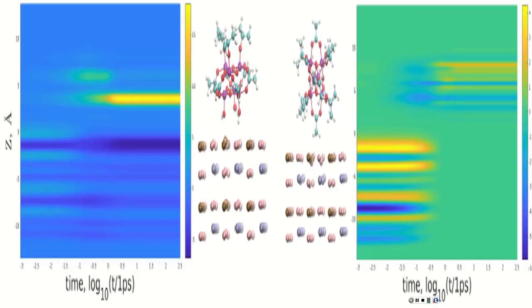And as time passes by, both electron and hole do migrate to titanium dioxide. So there is no charge transfer. Well, there is one very short transient charge transfer. By the way, it is similar to what Dan computed for your recent work. So, transient short period charge transfer, and then later lowest excitation, both blue hole and orange electrons stay on the acceptor. So final state is neutral.